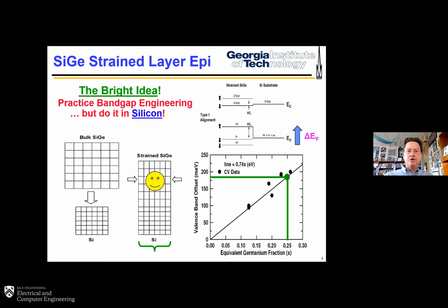This idea, by the way, of combining germanium and silicon is ancient. It goes all the way back to William Shockley's 1948 transistor patent. And it actually took almost 40 years to figure out how to do this. And the smiley face there shows how one does it. And that is if you compressively strain the germanium, silicon germanium alloy, you can get it to mate to the silicon underlying matrix in a way which is unconditionally stable and can be processed around and put onto a silicon wafer in a way that doesn't generate defects. That happened in the early 80s and took a few years to figure out how to put that inside a device, but that again took off the field in the late 80s or so.